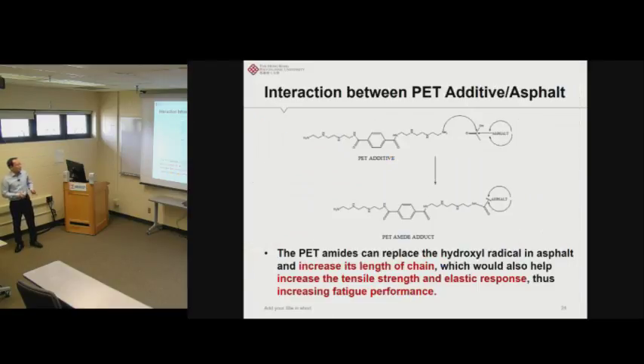So to find out the reason, we also did some literature search, and here are some of the potential reasons we found based on our literature search. On the top, you can see this represents the asphalt binder. In the asphalt binder, there is actually a group called the hydroxyl radical, similar to what we have done during the aminolysis process.